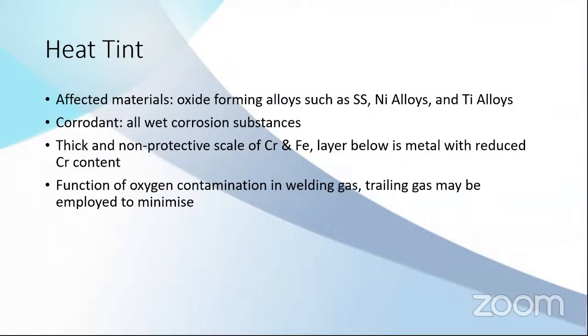So normally, if it's a very corrosive condition during the weld, we ask for the welding design to have the trailing gas to make sure that there is low probability of oxygen contamination.